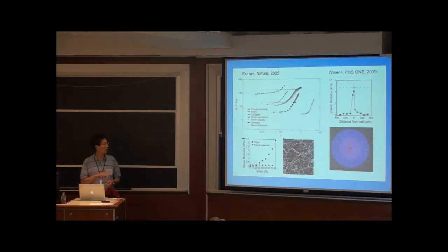So what happens is that as you align the material, as you strain it in a certain direction, all of the fibers initially move very easily because they're just bending. You think of spaghetti, easy to bend the fibers. But as the strain continues to increase, now you have all of these aligned fibers, and you reach a point at which the only additional strain that you're getting is not from aligning fibers, but is from stretching the fibers. And so the stretching can become quite stiff.